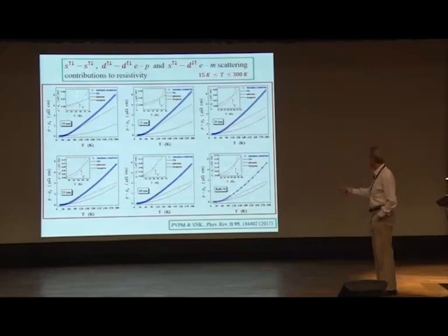For example, here it was about 30 Kelvin. For nickel, I mean bulk nickel, it's around 60. So it gives you an idea of how different scattering mechanisms become important in different temperature ranges, and you can even know their actual magnitude.